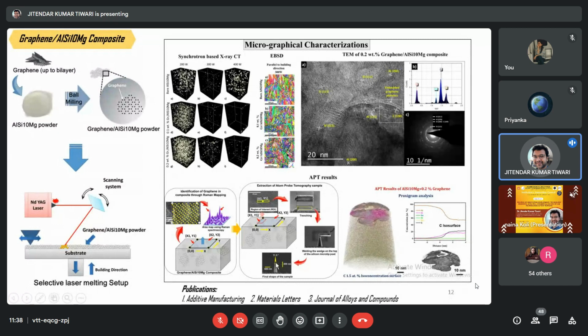And what happened, a pulse laser will fall on this particular tip, and atom by atom, every atom sublimates. After the sublimation, the atom will fall on the detector, and based on the time of flight and detector position, we can reconstruct the 3 dimensional structure of your material.